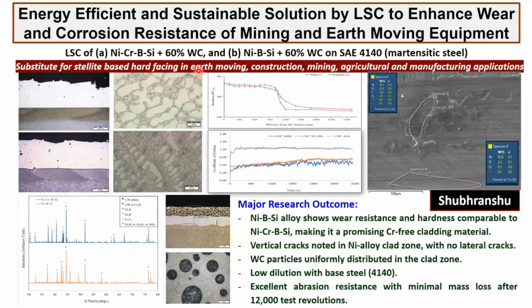So Shubhranshu is using, basically, if you have to compare these two alloys, one is with chromium and this is without chromium. He's able to prove that laser cladding allows nickel boron silicon to be as good as, in a way, better than nickel chromium boron silicon, because these nickel borides and nickel silicides make a very hard surface, which also makes it possible to avoid making such tungsten carbide dispersed composite alloys. So with this alloy alone, we can do a lot of improvement for earth-moving equipment and prevent wear and tear.